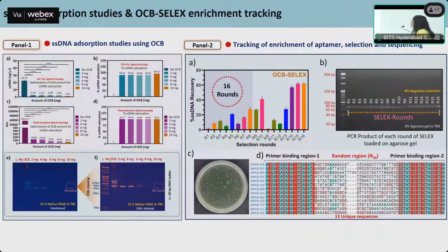Then we wanted to know how much OCB is required for the Selex process, because we cannot really do the experiments without some calculations. So we utilized different amounts of OCB and did UV absorbance, fluorescence and gel based analysis. We observed that 10 milligrams of OCB was sufficient for complete adsorption of the aptamers. Then 16 rounds of Selex were performed, together with negative selection after round 10.